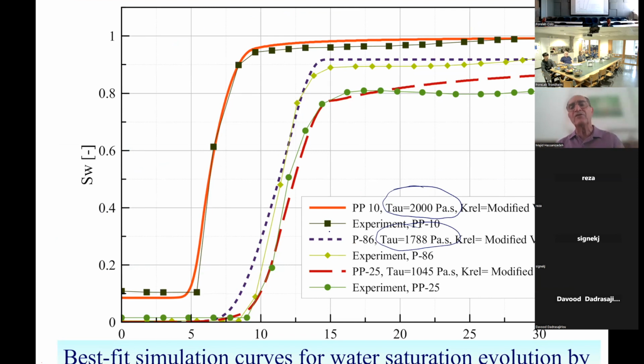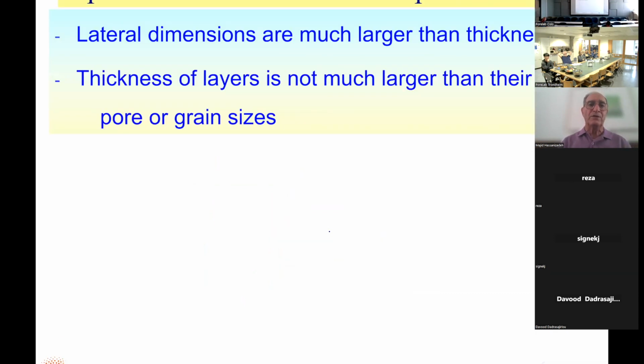So this is one of the things that differs from a lot of geological porous media. Processes often happen fast. In the pressing of paper pulp I mentioned to you, it moves through the paper pulp, and the felt moves between presses at tens of meters per second. And so the imbibition really happens very fast. Whereas for that felt, if you measure a PCS curve, you need a day to get the PCS curve. So processes happen fast, therefore the dynamic effect is often important.